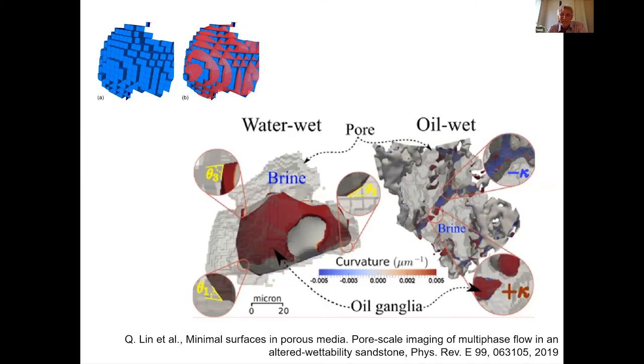What is really amazing in what people succeeded to do is that the resolution of their structural tool is such that at sub-micrometer level, they can measure the curvature of the meniscus between the oil and the brine phase. And what they discovered is that transport of the two fluids is the easiest when the average curvature of the meniscus is zero, which means that it has a perfect saddle shape. And at that point, the pore pressure vanishes completely, and you are able to move oil and move water or air as if there was no capillary pressure in the system.